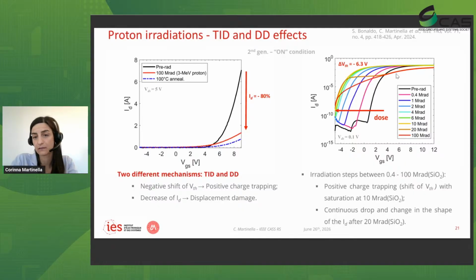By looking at the logarithmic scale of the transfer characteristic, we can see the shift of the curves, and then we can see a drop of it, so that there is a continuous drop until a saturation level. And so this was the onset of the displacement damage. What was happening in this device was that we were having charge compensation. So the carriers were trapped by the active defects that were created by the primary particles.